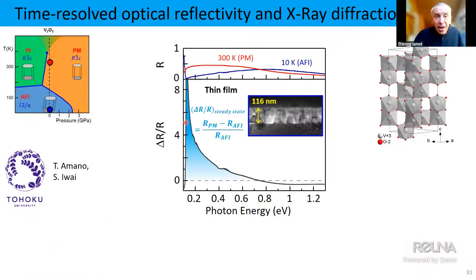So to check if we can induce an insulator to metal transition, our colleagues in Japan have done the following experiment. They have studied the reflectivity at steady state at room temperature, red, and at very low temperature in the insulating regime. You see these two colors correspond to these two points. And when you have these two reflectivity spectra, you can easily deduce the variation, delta R over R. This variation is the variation expected when you go from insulator to metal. The spectrum should evolve like this.